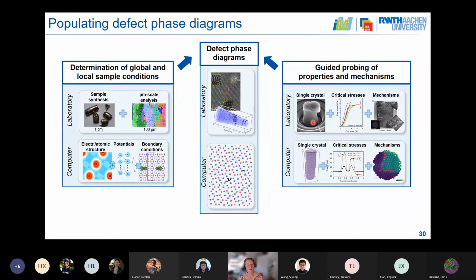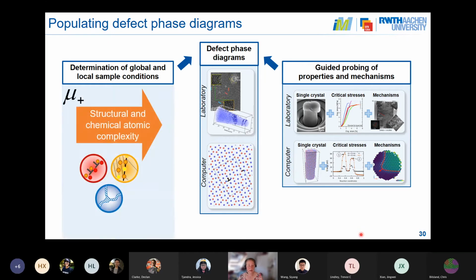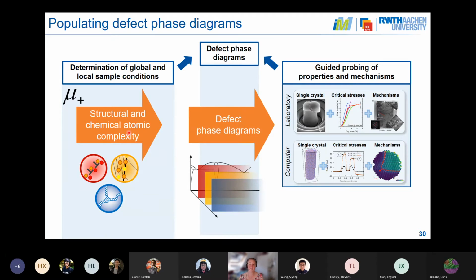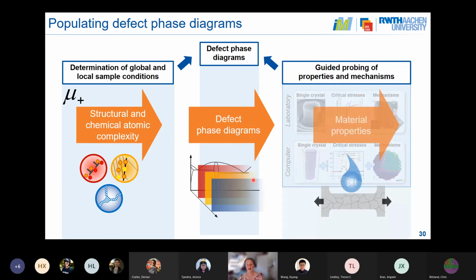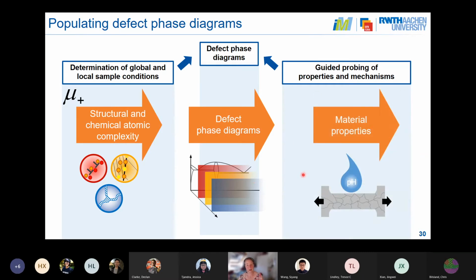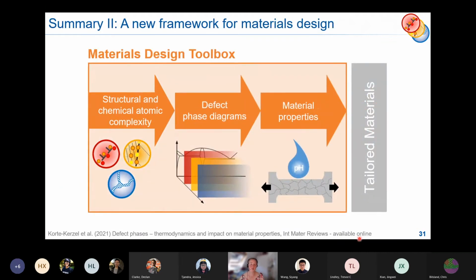And then we'll use different methods to look at the properties. For example, for dislocations, we'll again go back to small single crystals and look at how they deform, which mechanisms we get, which stresses we measure, and we can do again the same in the computer. That means at the end of the day that we're really starting here with the assumption that we have some structural and chemical complexity at the atomic scale, meaning these distinct structures that form that are related to a certain structure and chemistry. Once we have these at our point of origin, we can then describe the stability of these individual defects. So we can look at their competition also, and we can connect them to then predict material properties. And we think at the end of the day, hopefully this will be a stepping stone to get a new materials design toolbox to actually be able to tailor materials and, for example, co-tailor them for different mechanisms like corrosion and mechanics.